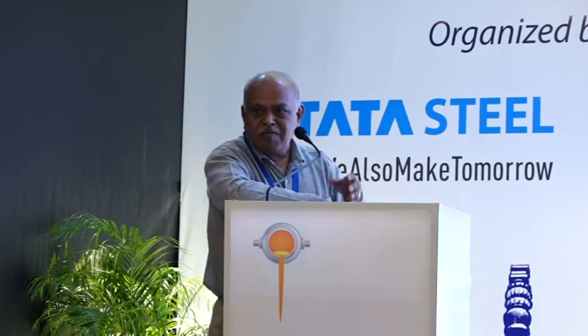Now, there are some issues that we need to address. We are in discussion. A test method for volumetric expansion of fine aggregate is not there anywhere in the world. It is there only for coarse aggregate. Fine aggregate, we are not aware. ASTM standard, Japanese standard, European standard, they all talk of coarse aggregate, between 0 to 35 mm. So for fine aggregate, when we make sand, obviously it doesn't fit in that, so we need to establish this procedure.